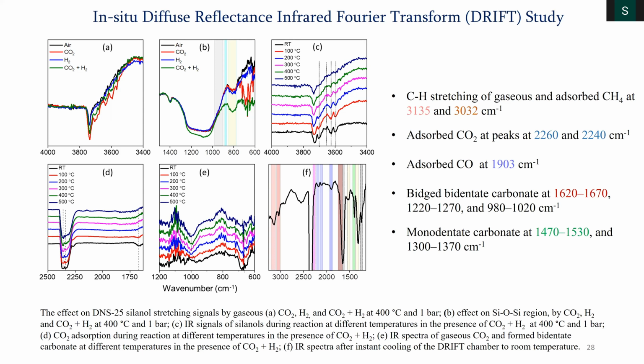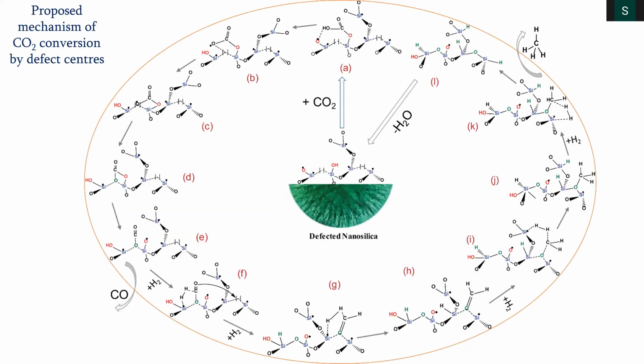And based on this data, which again I'm skipping, not going into more technical details, we came up with this proposed mechanism where we showed that the O radicals and the silanols activate the CO2 like this. And then here, the Si radicals, the E' centers, are the ones which dissociate the hydrogen. See here, Si interacts with hydrogen with the help of this precarbonyl, which is coming from the CO2. And then you see now it is dissociated. That bond is broken. You get SiH, and that H goes to the carbonyl, and you form this pre-formyl